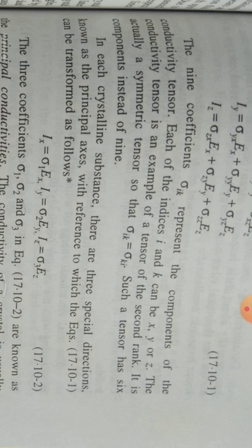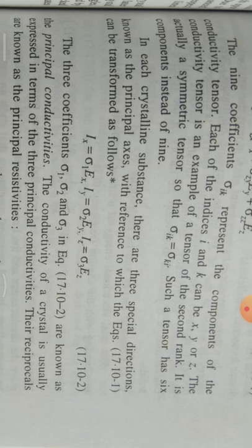Each of the indices i and k can be x, y, z. The conductivity tensor is an example of a tensor of the second rank. It is actually a symmetric tensor, so that sigma ik is equal to sigma ki. Such a tensor has 6 components instead of 9.